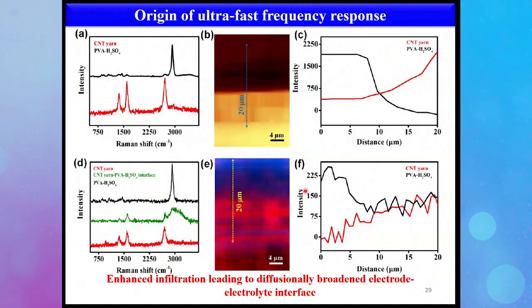Tapas Das says, I was wondering about the synthesis process of CNT in wire form. What is the mechanism of formation? You basically use a vertical CVD furnace. You put in the carbon source and the catalyst from the top, and as it slowly comes down, there is a process of CNT formation, and it ends up like an aerosol kind of material, and then you start pulling it out. It's exactly like how the shopkeeper makes cotton candy. He puts in sugar cubes, heats it up, and then slowly winds it around the circumference. It's a similar way that we draw out the wire from the growth chamber.